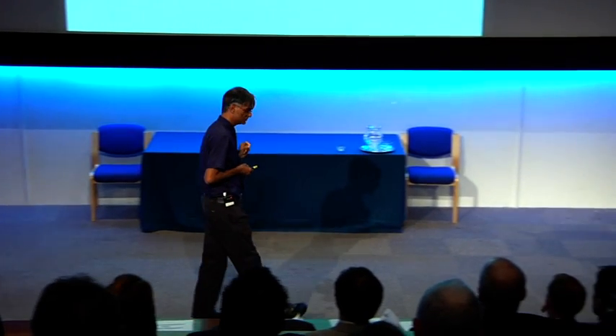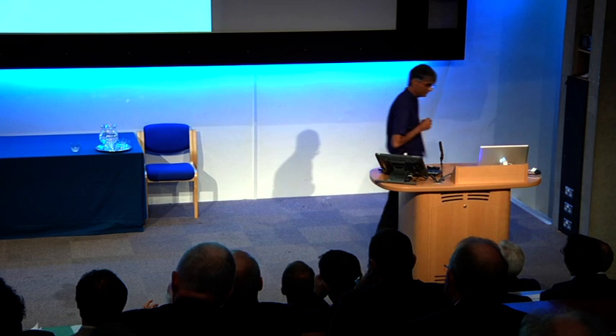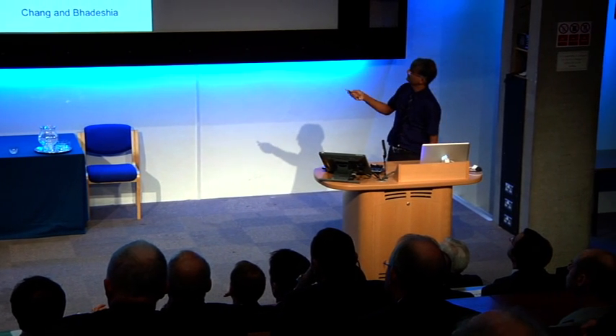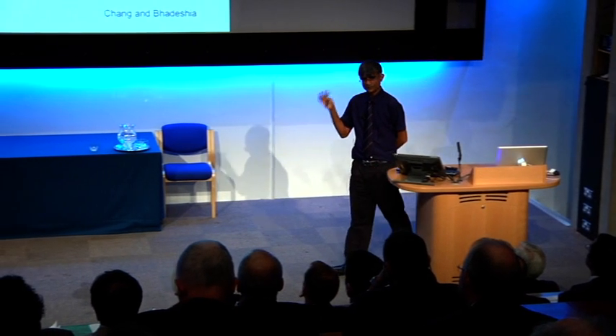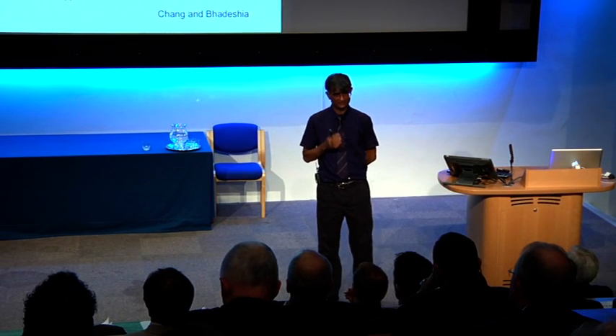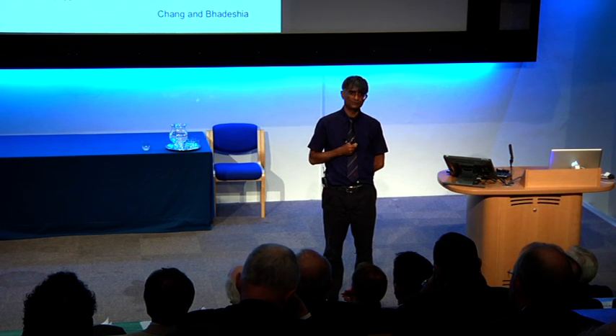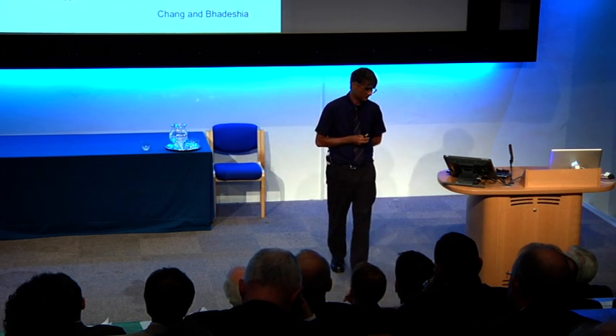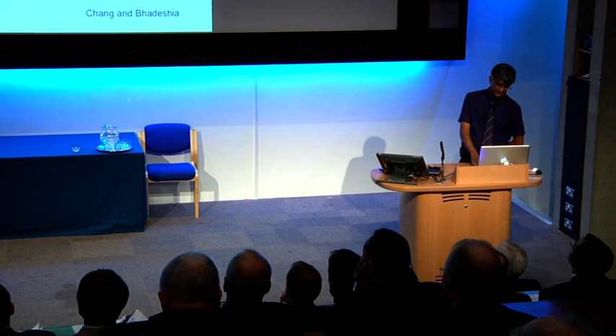Okay? So you are left with the loose packing of the prior austenite grain boundaries in the final structure, and that means that you can get segregation of impurities at those locations much more easily than in the softer steels. And then you get failure at the austenite grain boundaries. Now, we can't really remove phosphorus easily, it's expensive to do, but if you add molybdenum, this is a very, very well-known effect from 60 years ago, then that effectively kills the effect of phosphorus. And then you can get better toughness and a lack of failure from the austenite grain boundary.